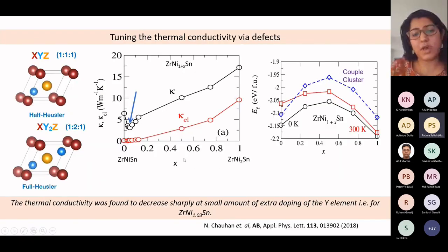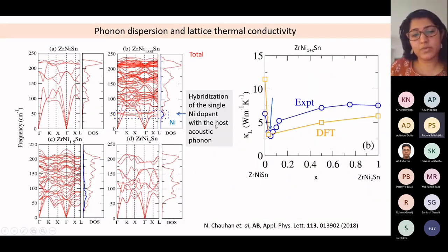So in principle, the Y site substitution is also good if it is limited to a very small amount of Y site substitution, because that will drastically lower the lattice thermal conductivity, which has been shown in this figure. So where Y site substitution has been done, the lattice thermal conductivity has been lowered, and that also very drastically, because the electronic part is not changing. So we studied this phenomenon in more detail.